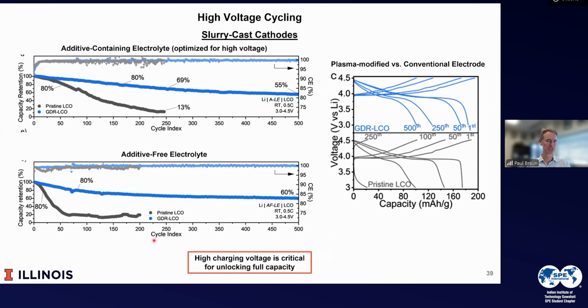And we observed a dramatic improvement. So if we take a very good electrolyte and then go to high voltage, after 250 cycles, only 13% capacity remains. If we do the surface treatment, 55% capacity retains after 500 cycles and almost 70% after 250. And when we take an electrolyte which is not improved, so this is additive free, the conventional material basically fails in 50 cycles, while this still has substantial capacity after 500 cycles. And we can see just the difference here. This is the first, the 50th, and the 250th cycle. Here's the first, the 50th, and there's the 250th here. So by 250 cycles, it's completely faded.